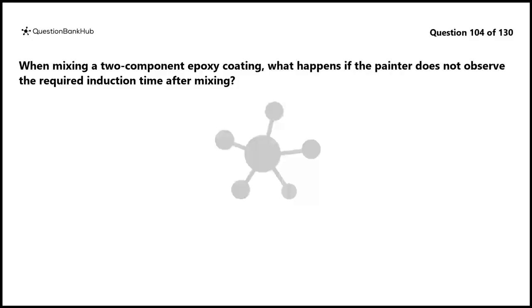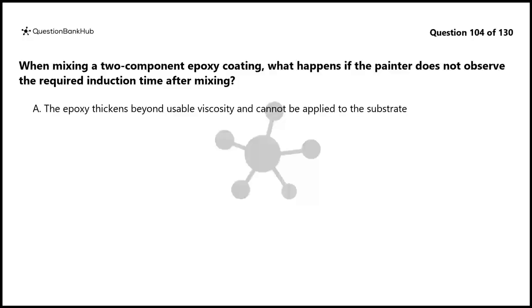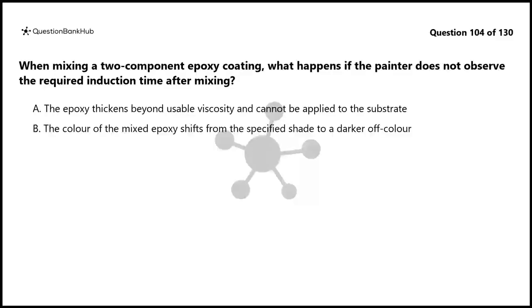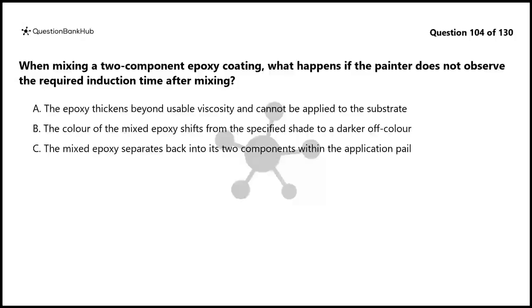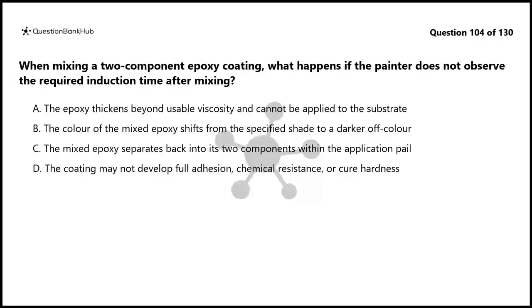Question 104. When mixing a two-component epoxy coating, what happens if the painter does not observe the required induction time after mixing? A. The epoxy thickens beyond usable viscosity and cannot be applied to the substrate. B. The color of the mixed epoxy shifts from the specified shade to a darker off color. C. The mixed epoxy separates back into its two components within the application pail. D. The coating may not develop full adhesion, chemical resistance, or cure hardness.